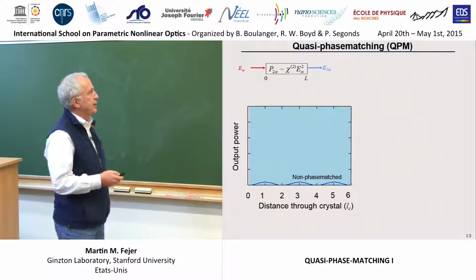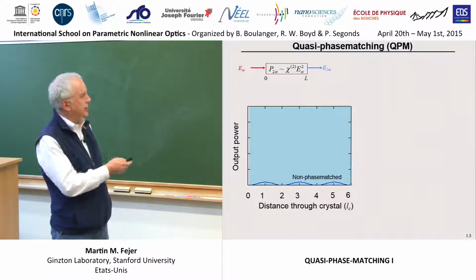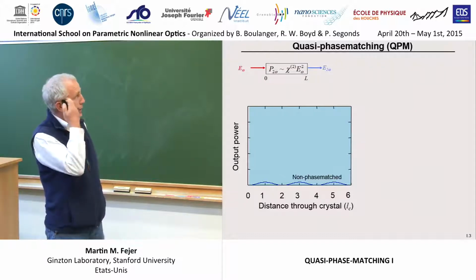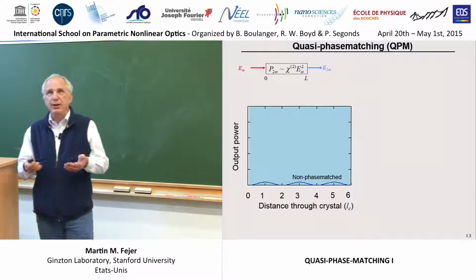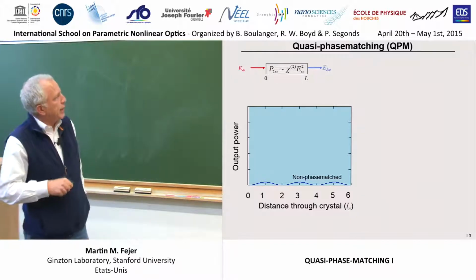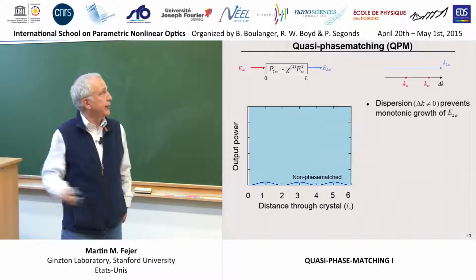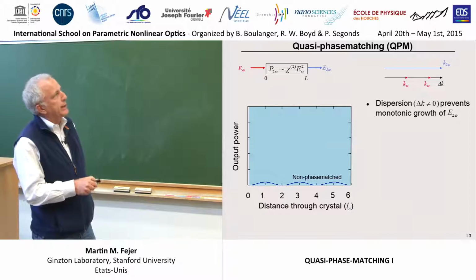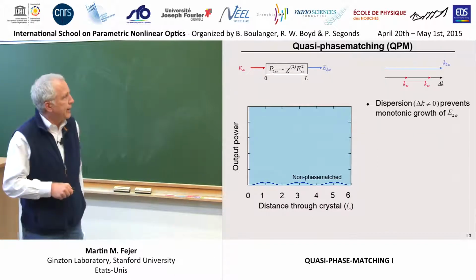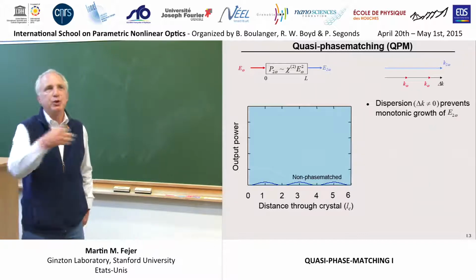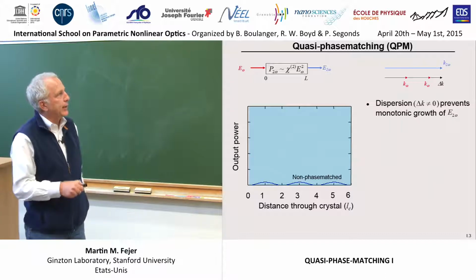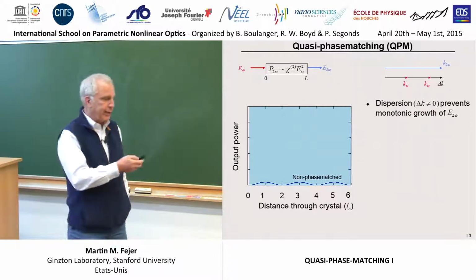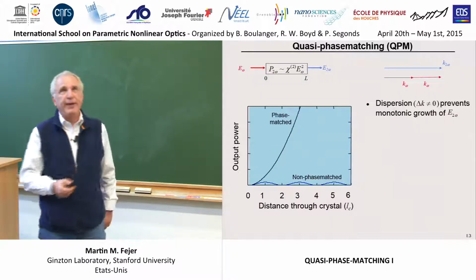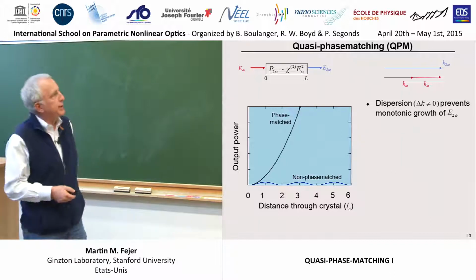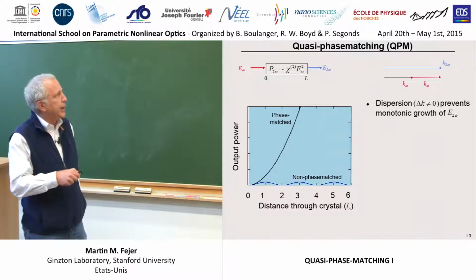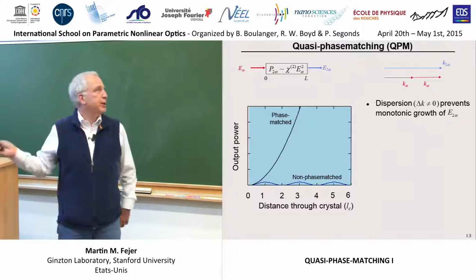In a conventionally phase matched device of some length L with a certain nonlinear susceptibility, if we use second harmonic generation as an example of the nonlinear process in question, if we don't have phase matching, that is, if the sum of the two k vectors destroyed is not equal to the generated second harmonic k vector, then there will be an oscillatory exchange of energy between the harmonic and the fundamental with a characteristic length that goes reciprocally with that phase mismatch delta k. If you happen to be able to phase match via the birefringence schemes that have been discussed already several times, then you get monotonic growth of the second harmonic intensity, and that's the most attractive situation.